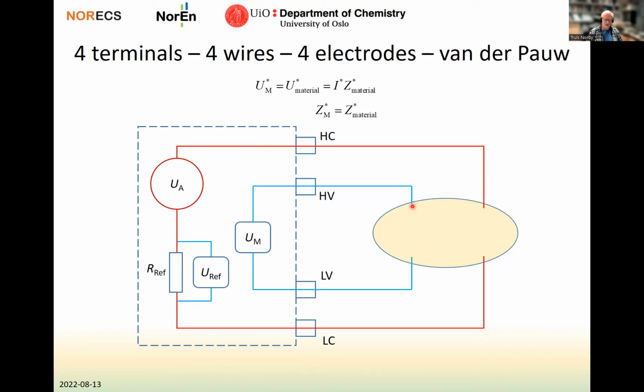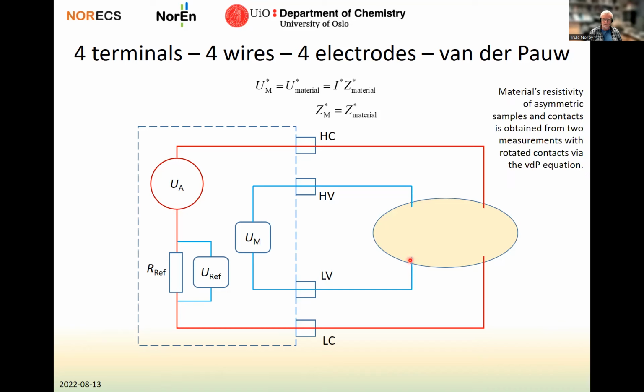And under certain conditions of these being close to the edge, there is something called a van der Pauw equation that can calculate the resistivity of the material based on the ratio between the current and the voltage. And this equation holds also for asymmetrical contacts and asymmetrical disk shapes.